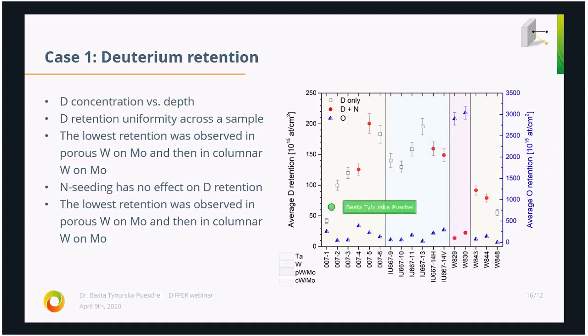So when we look at the retention data, which are those symbols here, then we can see that deuterium retention is the lowest in the porous tungsten, then somewhat higher in the columnar tungsten, and in terms of tantalum or tungsten substrate, the deuterium retention is comparable. Then some of the samples were exposed to pure deuterium only, and some were exposed to deuterium seeded with nitrogen. And the nitrogen data are marked red, and you can see that at least here where the deuterium retention is comparable between tantalum and tungsten samples, you see no difference in deuterium retention with the nitrogen seeding.